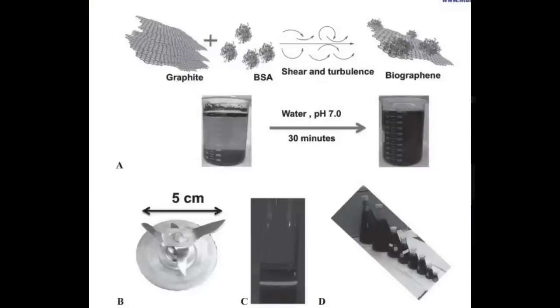If you want to separate it out, you need to centrifuge it 45 minutes at 1500 RPM. Now the proteins, which now coat the graphene, prevent it from restacking, so you'll get a dry powder that way. If you're going to use this, I wouldn't bother. I mean, it's already really nicely dispersed. Just chuck that in some sand and cement, and you're going to have yourself a graphene-improved concrete.